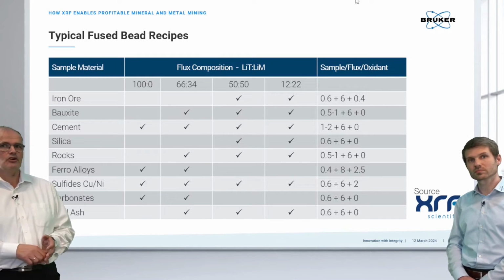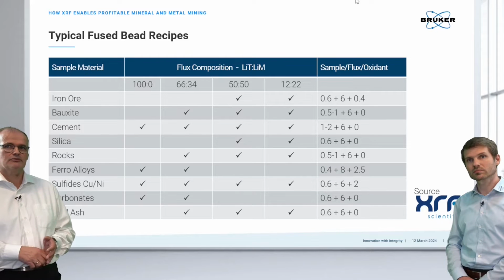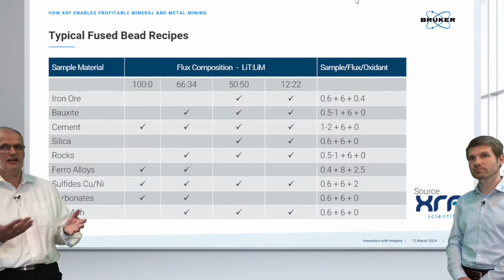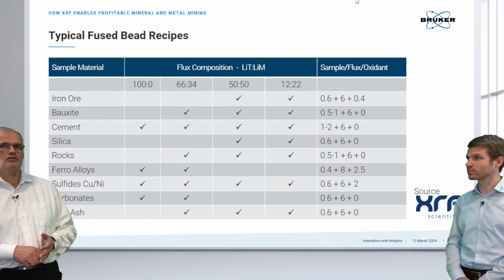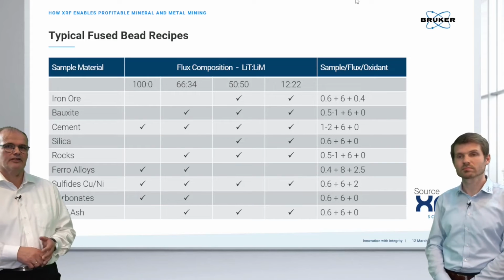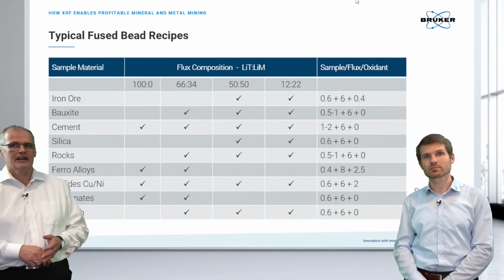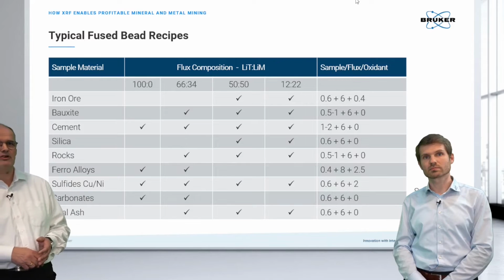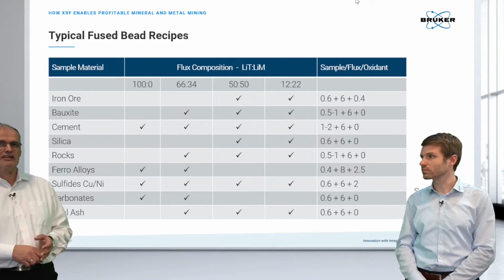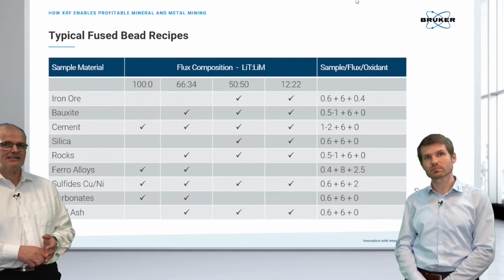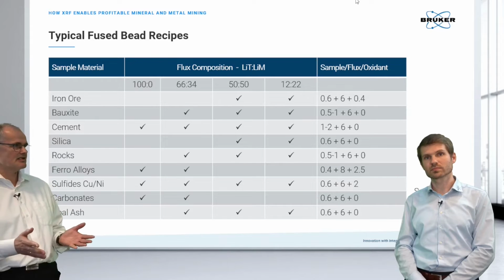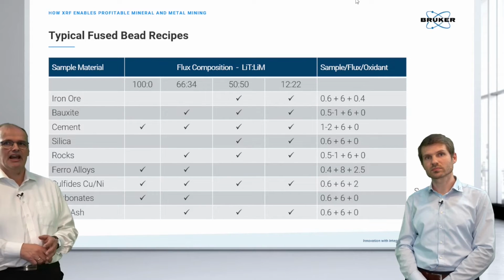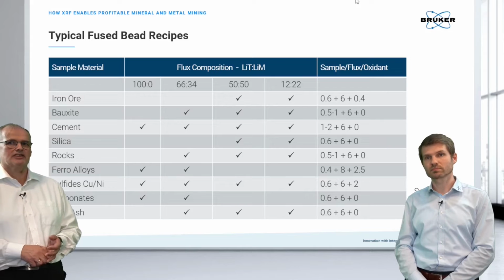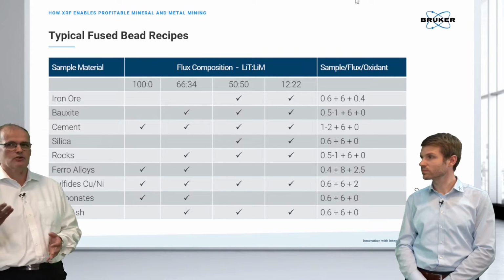When we look at iron ore, there we prefer to have a 50-50 ratio. And also we will add some oxidant in terms to protect the platinum ware and also help with the dilution of the sample. Pretty tricky, in other words, are the sulfides. There we need more oxidant because of the sulfur. So actually there is a little bit of complexity in these recipes. The nice thing is they are already available for the machines. So actually it's a pretty straightforward way, just following this guideline.